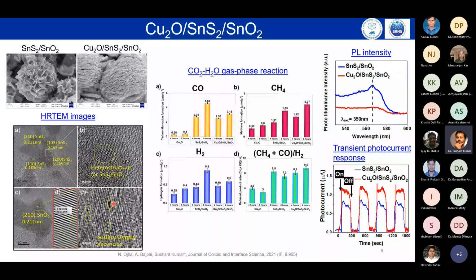The reason why I'm repeatedly telling you about the oxygen vacancies is that there is still an argument whether these oxygen vacancies help in the reaction or retard the reaction. That means whether these sites act as recombination sites, or host one of the electrons or holes and let the other species, either electron or hole, go and reach the surface of the photocatalyst.